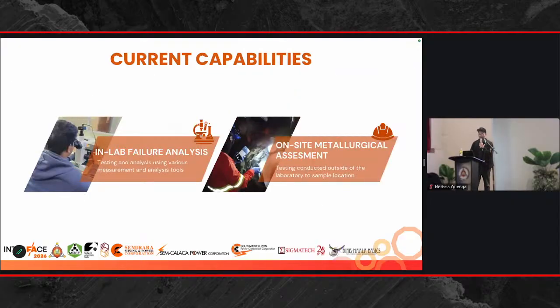So far, our core capabilities encompass both on-site and in-house laboratory testing, allowing us to evaluate materials and investigate failure comprehensively. On the field side, we provide field metallography or replication testing, which is a non-destructive technique that enables the examination of microstructures directly on critical components while they remain in service. This capability is particularly important for condition monitoring and the early detection of degradation mechanisms such as creep, carbide degradation, and even crack initiation. It helps industries make informed maintenance and operational decisions without requiring component removal.